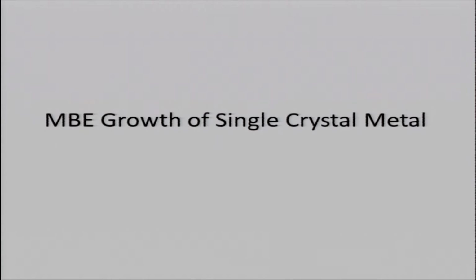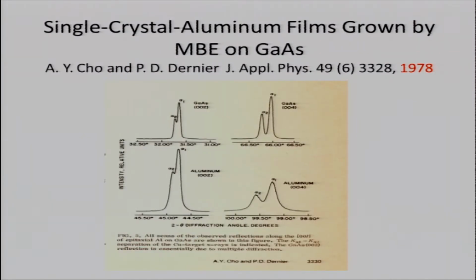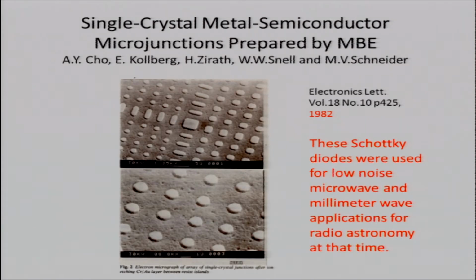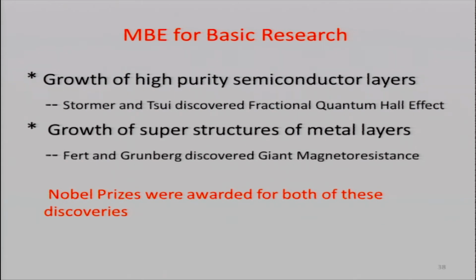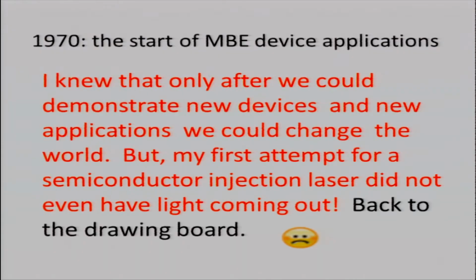Now, with the time limit, I want to continue to introduce MBE growth of single crystal metal. We grew single crystal aluminum on gallium arsenide. And with that, we made micro Schottky diodes, which have extremely low noise temperature. At that time, this single crystal Schottky diode was applied in radio astronomy. MBE's contribution to basic research is also quite extensive. For instance, the growth of high purity gallium arsenide semiconductor layers, where Horst Stormer and Tsui discovered the fractional quantum Hall effect, and the growth of superstructures of metal layers, where Fert and Grunberg discovered giant magnetoresistance. Nobel Prizes were awarded for both of these discoveries.